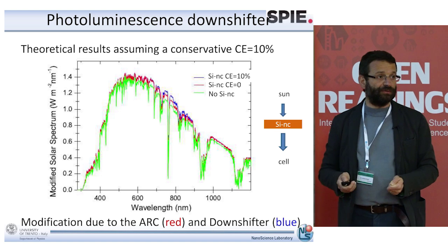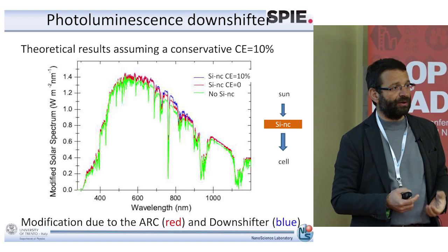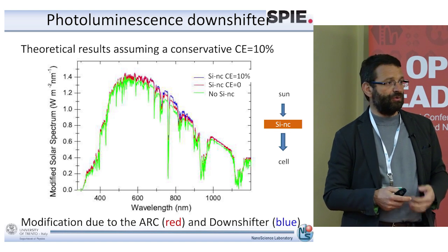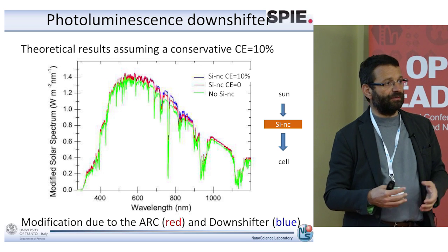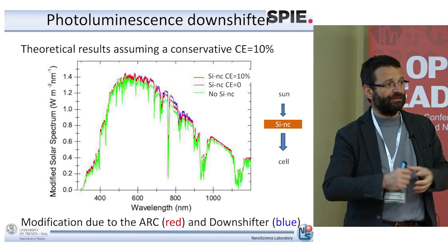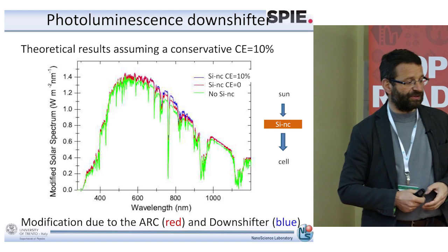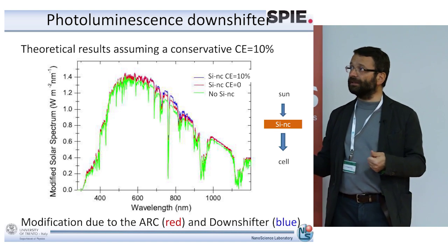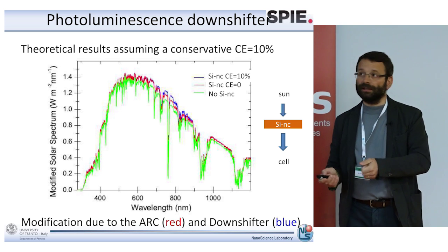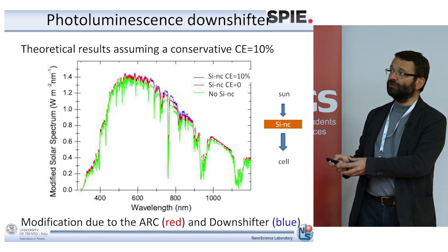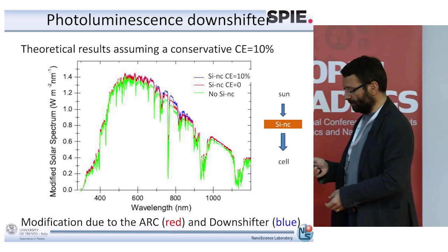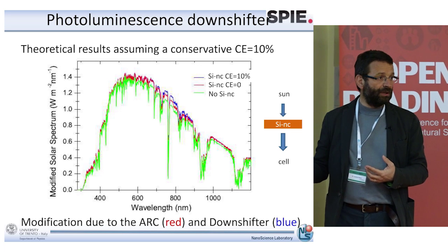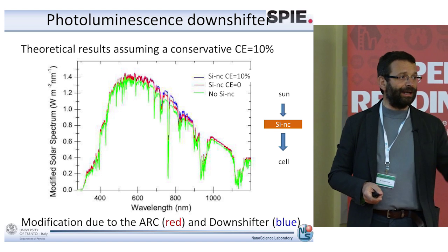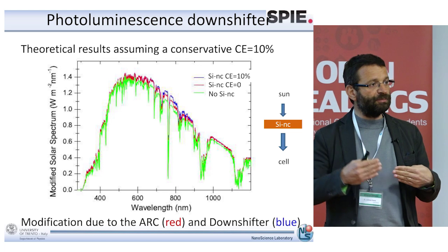And here you do see a change. You see the green and the red are different. And the reason why the green and the red are different is because the nanocrystals have a different refractive index than the silicon. So you have an effect that is called an anti-reflection coating effect. So by controlling the thickness of the nanocrystal layer, you reduce the reflectivity of the silicon cell. But then, if you add the fact that the nanocrystals can emit light, they do emit light in the red, and so you now see the blue line here. And so you see that more light is coming to the cell in the region where the silicon internal efficiency is larger. And so in this way you can hope to increase the quantum efficiency of the cell. Actually those are calculations, and in this calculation we made the hypothesis that of all the light absorbed by the silicon nanocrystals, only 10% is re-emitted.